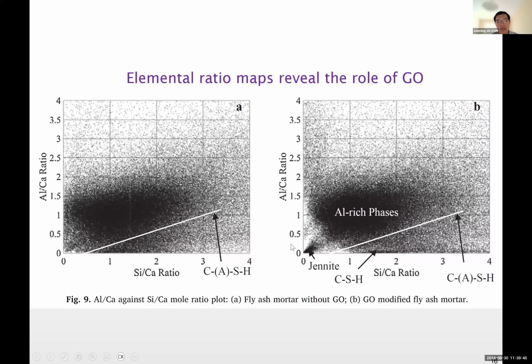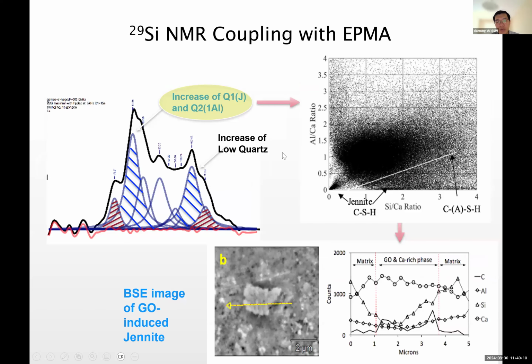For instance, the one on the left is without graphene oxide, the one on the right with graphene oxide, and you see this jennite-like material showing up in this corner. And again, in the case of fly ash-based geopolymer, it's not just CSH gel, it's actually more like CASH gel. A stands for aluminate. So again, we have different tools to shed light on the same story. Again, NMR, EPMA, and this one, EPMA, can also scan through. I mean, EPMA has different modes, like under the BSE or backscatter electron mode, you can have this image, and that seems to indicate a jennite particle.